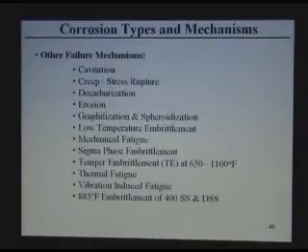Graphitization, this is the carbon in the steel forming graphite, so the steel loses strength, or it forms spheroidized structures in certain areas, I will show the picture. That's why your carbon steel, we don't use it above 800 because of this mechanism.